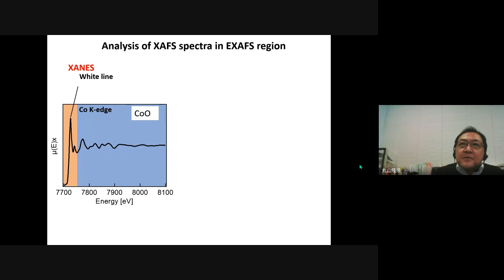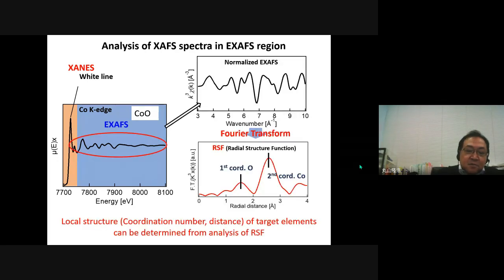So after background subtraction and Fourier transform, we obtained radial structure function, RSF. Furthermore, by curve fitting analysis, we determined local structure of target element, such as coordination number and bond distance. So we can get information about local structure of target element.